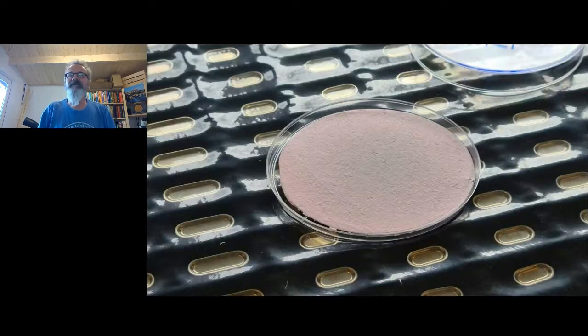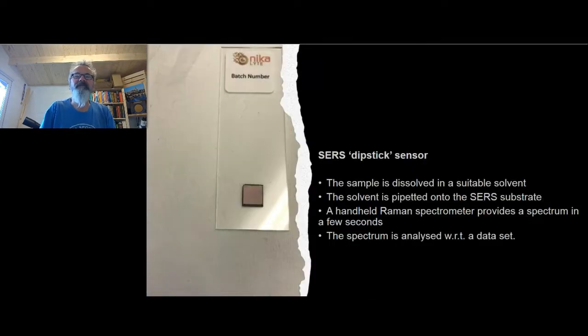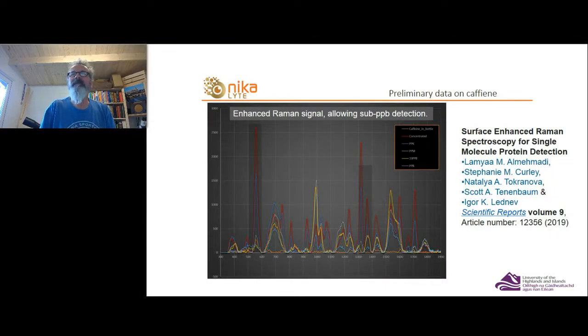So I showed this substrate earlier, and this is our pink nanoplasmonic gold surfaces. So now we've got our substrate that we might be able to use to amplify our Raman signal. So what we do with that is we turn it into a dipstick. So we take a bit of our Raman amplifier material, we put it onto a dipstick, and then simply what we do is take a sample of the material we want to look at, we put it into a solvent, say some water, and we drop it onto the surface, and then we measure the Raman